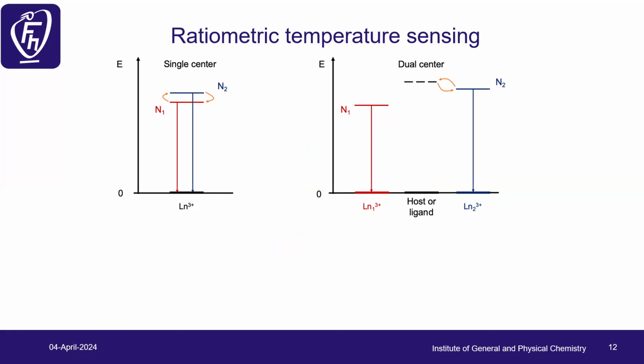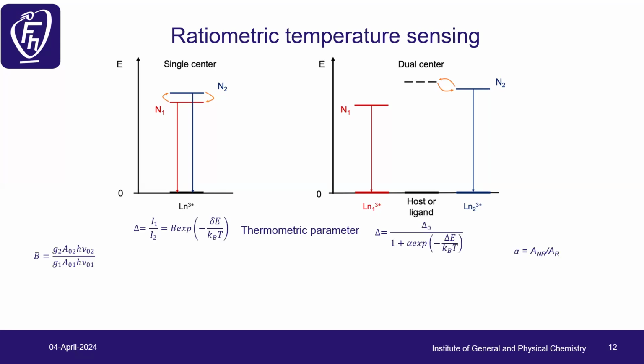And there we also have two types. One can be on a single center, so we can have only one ion, such as dysprosium, which can have two different populated excited states, and then from there emit at different wavelengths. Or we can have two different lanthanide ions. The systems that I will show are terbium europium and terbium samarium, where they are communicating because the distance between each other is short. Here are some thermometric parameters. This is the Boltzmann equation, and the second one is the Mott-Seitz one, where alpha is the ratio between non-radiative and radiative quenching.